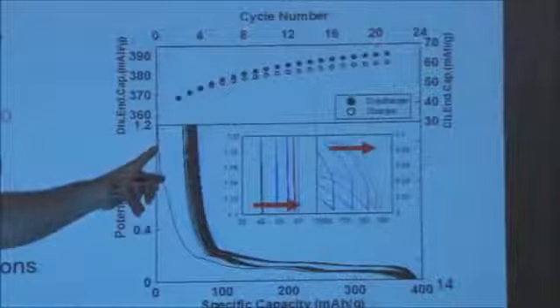So you can take a look at this reaction between the lithium in the graphite and the electrolyte solution by studying a lithium metal versus graphite cell. In this lower panel, I've plotted the voltage of a lithium-graphite cell as you add lithium to the graphite and then remove it again. It goes back and the voltage comes up again. But if you notice, you don't come back to zero on the capacity axis.